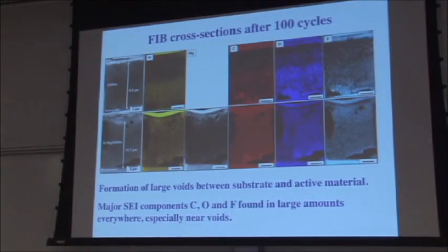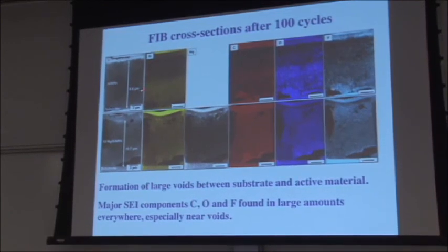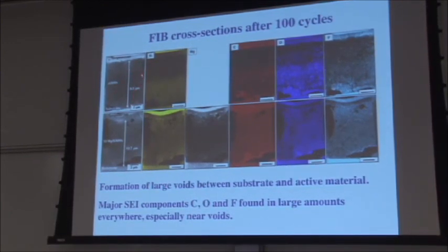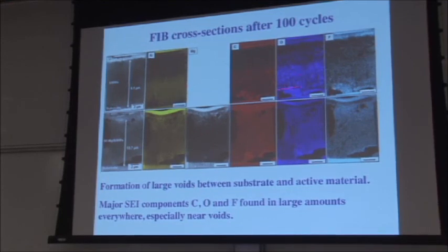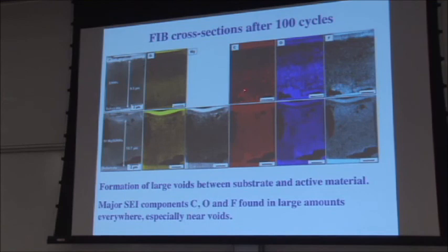And why isn't there an improvement? Well, what we see, so this is your 100-cycled FIB cross-section of the magnesium-coated silicon nanowires. And what you see is there's really no silicon nanowire left. It's just this giant agglomerated thin film clump of silicon, magnesium, and SEI layer all interspersed, with significantly enhanced levels of SEI layer formation near these type of voids, which were representative of the whole microstructure.